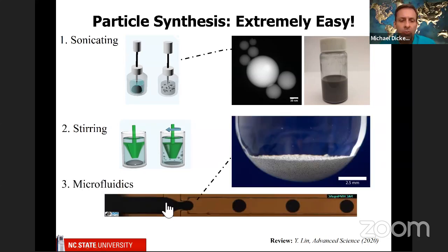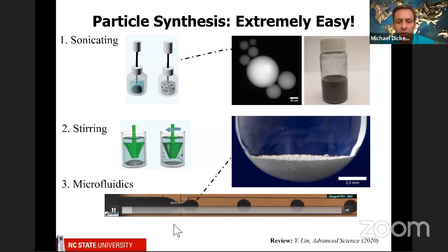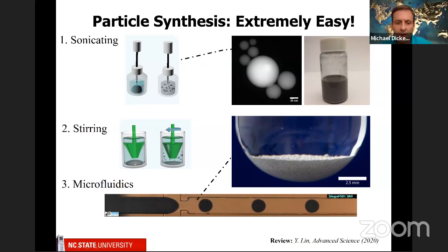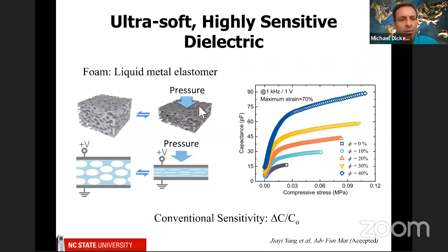And then you can also use microfluidics. So this video shows, it's a high speed camera video showing us squeezing liquid metal, which appears black here because it's backlit, through a little orifice. And you can make 100 micron-ish droplets that are very stable due to this oxide layer. So we actually use this stirring technique to make a liquid metal foam. So this is a conceptual idea of what we're doing.